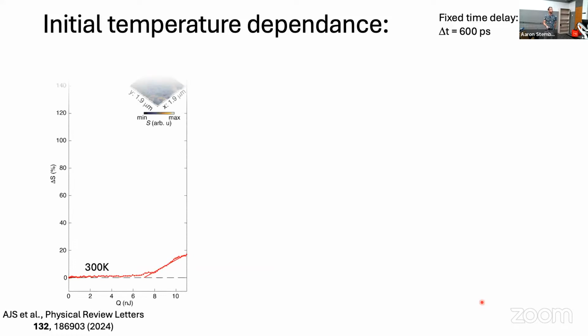depends on temperature. So first, what we're going to do is fix the time delay at 600 picoseconds after we have photoexcited the system, giving it plenty of time to grow and nucleate and do whatever it's going to do. And also not giving it enough time to cool back down to the initial insulating state. So that cooling process takes about 10 nanoseconds.